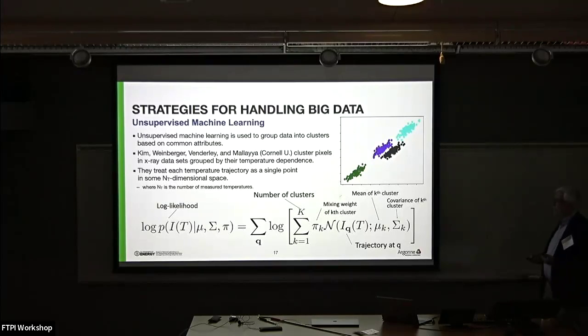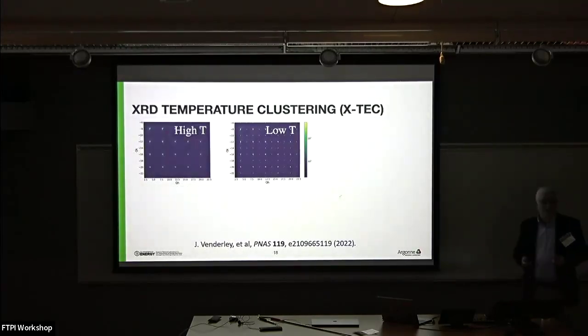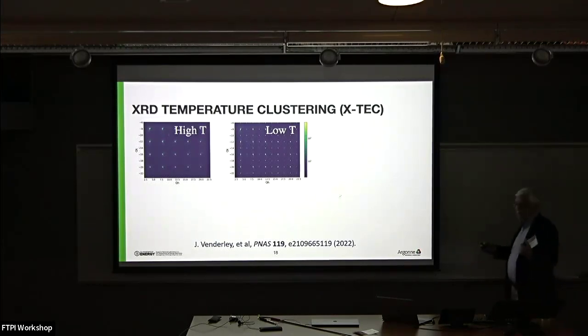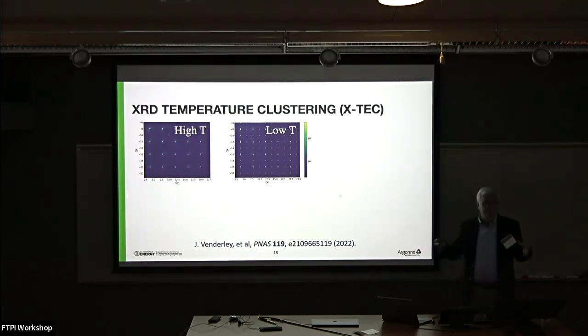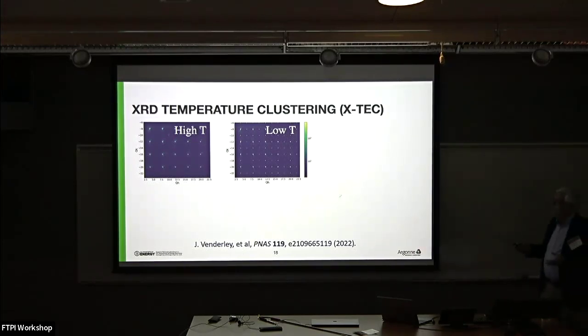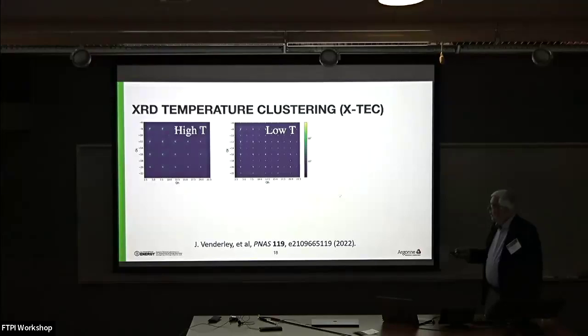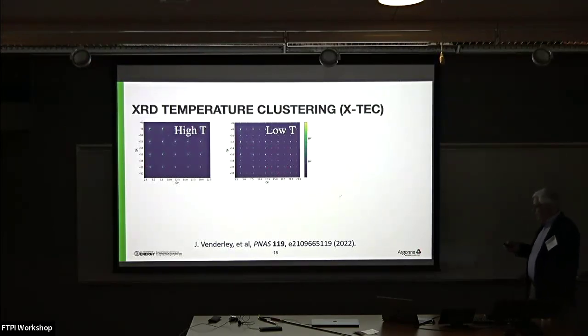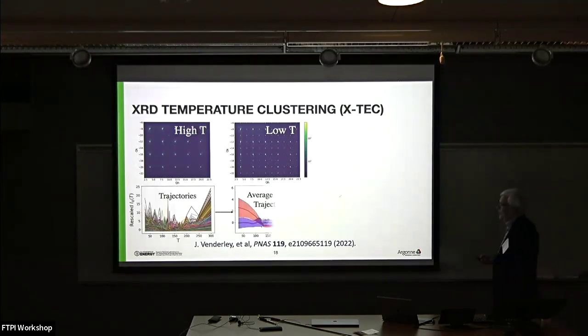But the insight that Eun-Ah Kim and her colleagues at Cornell had was that this is ideal for studying systems where you're measuring the temperature dependence over a large number of temperatures of a set of voxels which you consider to be statistically independent from each other. So supposing we have something which goes through some kind of structural phase transition, could be a CDW or something else. Okay, so at high temperature you see one set of Bragg peaks, at low temperature you see extra superlattice peaks appearing. All of the voxels that correspond to these superlattice peaks would all turn on at the transition temperature.